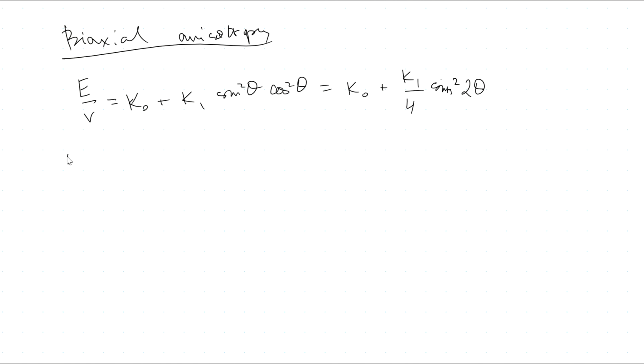The torque by the effective anisotropy field on the magnetization is K1 over 2 sine 4 theta. And it is more convenient to plot it. So let's say if you take X, Y, but again, let's not use X, Y, since we already know this. This would be direction 1, 0, 0.